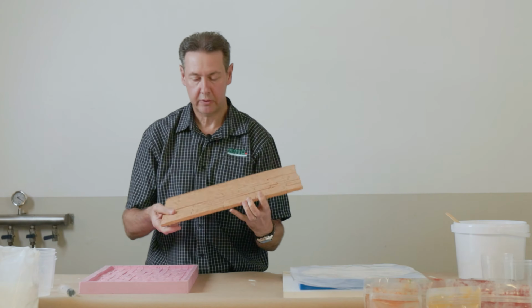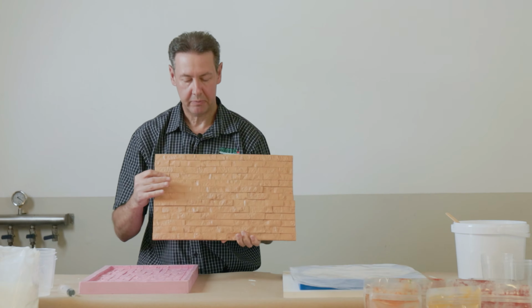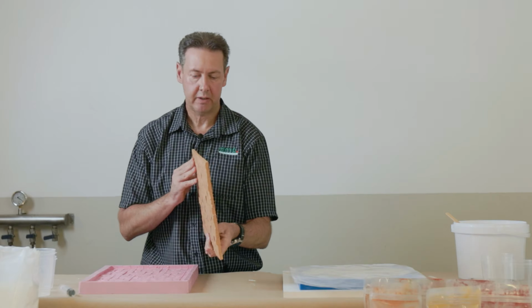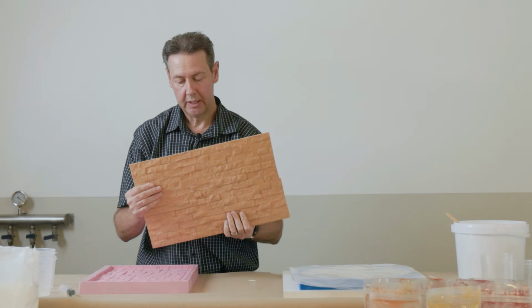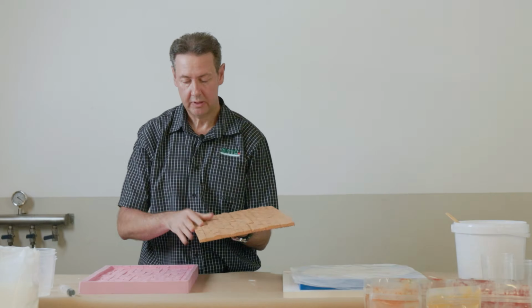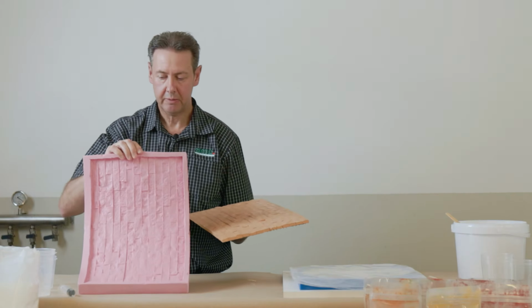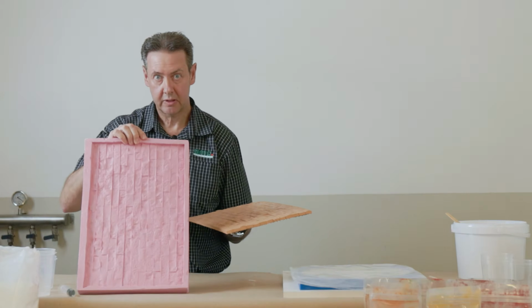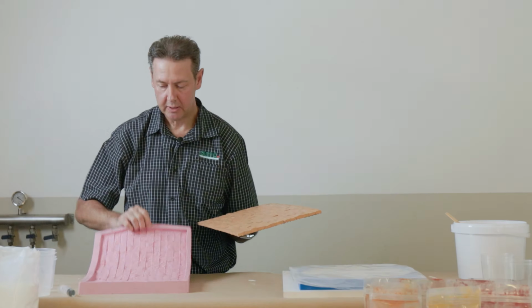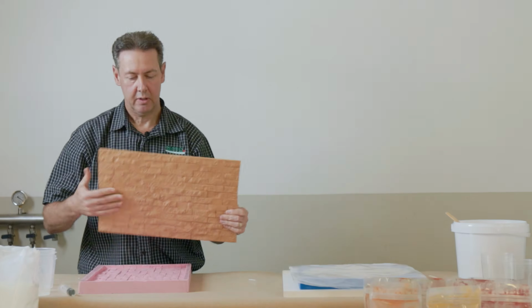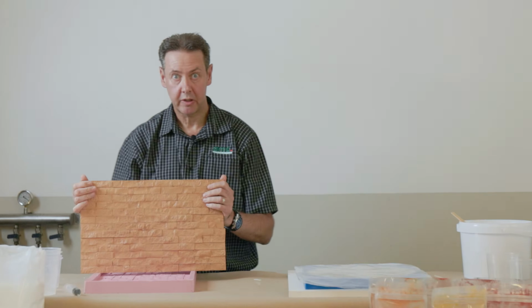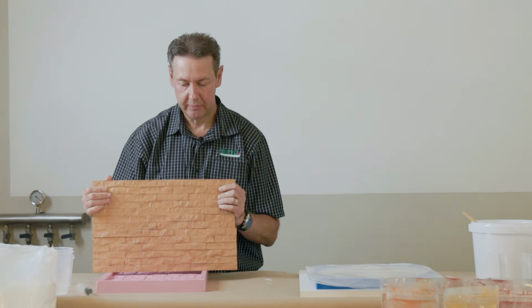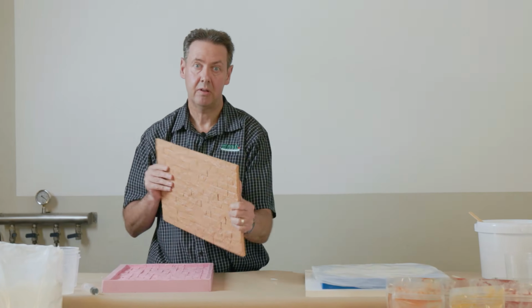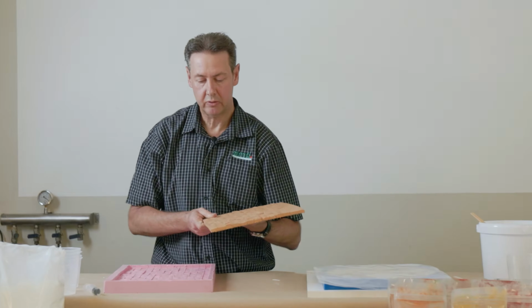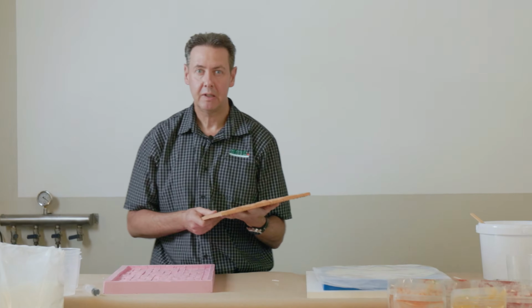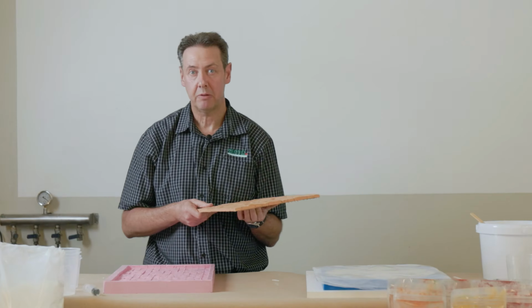So here we have a GFRC panel. As you can see, this panel is quite thin, probably only about 8mm thick, and super strong even in this thickness. That came out of this little silicone mold over here. So this is a TinCure silicone mold, Mold Max 30, and the whole main reason for using glass fiber reinforced concrete is so that we have the fiber reinforcing in to do thin, lightweight pieces that have some really good strength. So the average laminate thickness is typically about 20 to 25 millimeters if you're doing a tabletop or countertop.